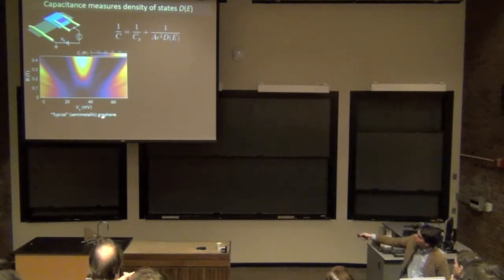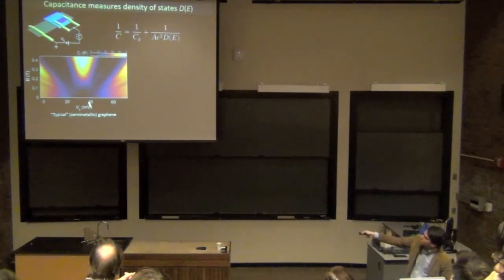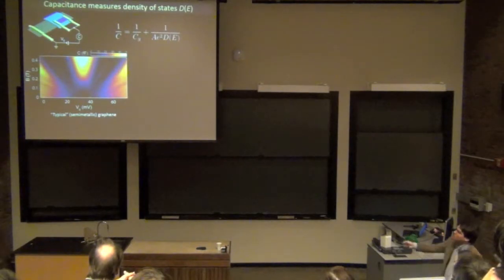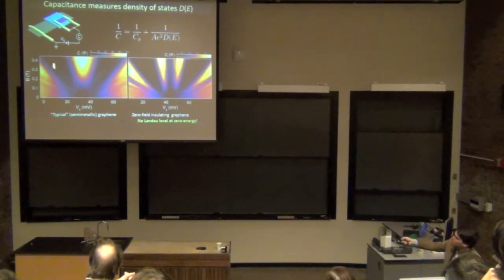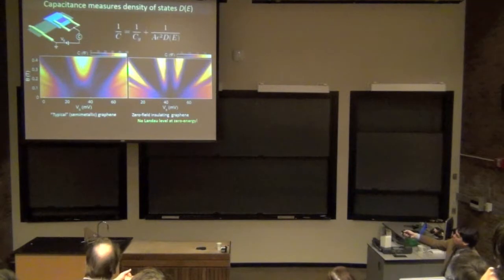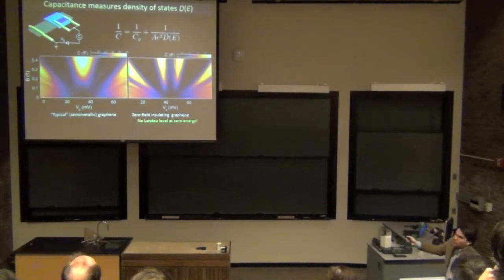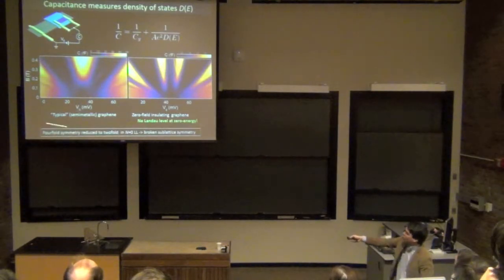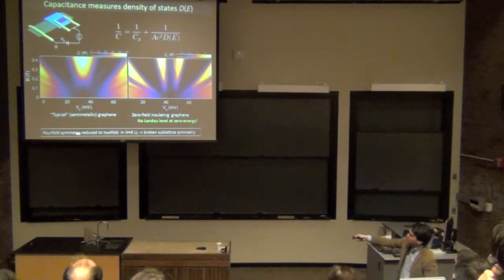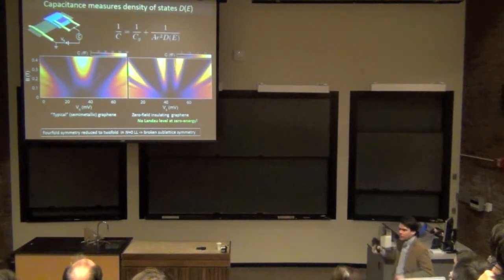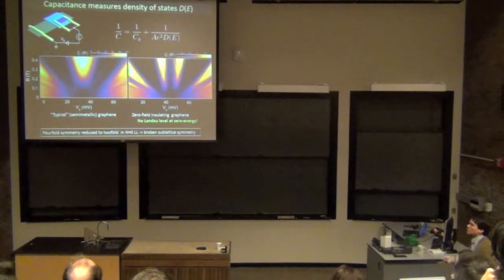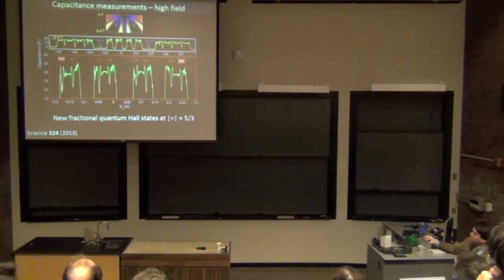And so this is now what a trace of these Landau levels looks like as a function of magnetic field and gate voltage. And you can see in a typical semi-metallic graphene structure the formation of this zero Landau level exactly at zero energy. What happens when we do this with our graphene that is insulating? What we see is something very different. We see that this normal fourfold degeneracy of the lowest Landau level has been split. In fact, this Landau level never really appears at zero energy. So this fourfold symmetry of the lowest Landau level has been reduced to a twofold symmetry, which points to lifting of one of the two symmetries, probably the sublattice symmetry. I'll skip that, but we saw some new fractional quantum Hall states too, if anybody wants to talk about that.